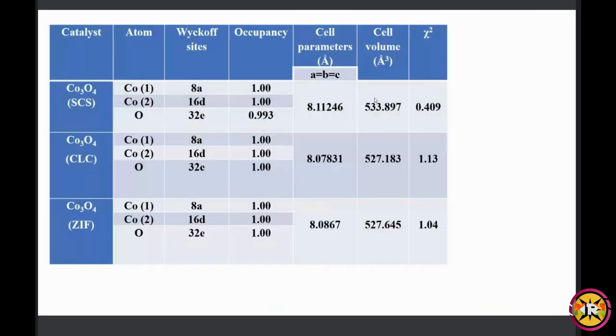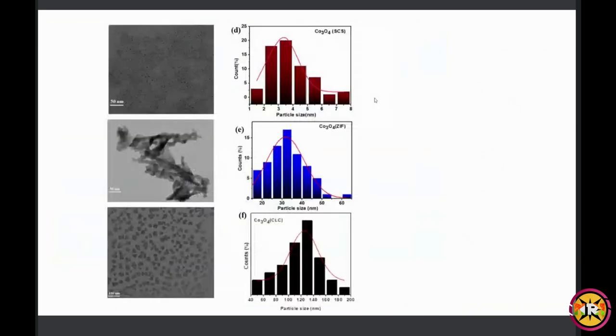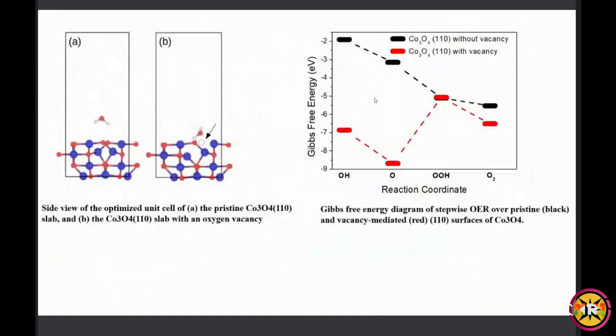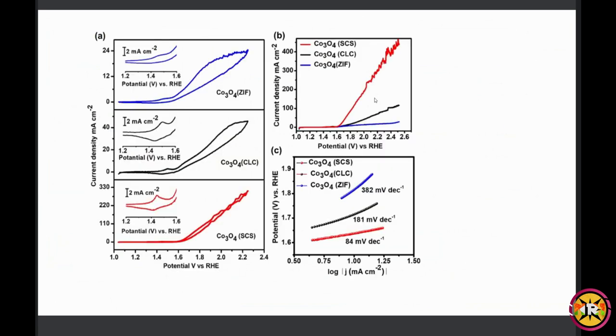This is what we have shown from Rietveld refinement and also from XPS. And DFT calculations have shown the difference of the reaction coordinate path with oxygen vacancy and without oxygen vacancy. Now coming to the electrocatalytic activity. In figure 1, I have done the cyclic voltammetry at the potential window 1 to 2.4 volt versus RHE, and here you can see the red one, Co3O4 SCS, is showing current density 330 milliampere per centimeter square, where the other two are showing only 30 and around 60. So it is quite higher than the other two.